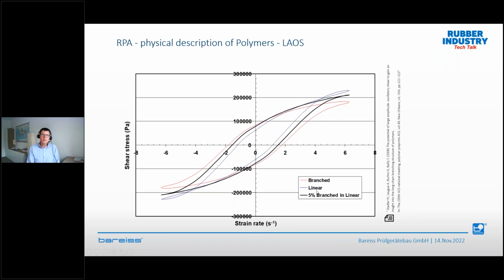And if you have linear polymers, you have something like here, these so-called secondary loops. And as soon as you have some small branching inside of your polymer, these secondary loops disappear. And if you have a lot of branching, you see you have these broad Lissajous figures. And this is something very nice and informative that these gentlemen found already in 2008, and very helpful, and which I know polymer suppliers, for example, are already using every day.